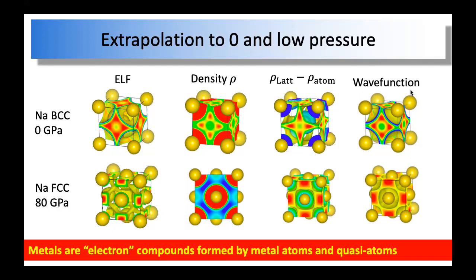And you can also clearly see the wave function, the crystal orbital. If you take the gamma point, you can see a particular wave function. This one is closest to the Fermi level, but it's an occupied orbital. And you can see that this one also has a maximum at these tetrahedral centers, showing that the electrons occupy these states, right? It's even clearer for FCC. If you look at FCC at 80 GPa, apparently it has a maximum at this octahedral site. It also has some, to a smaller amount.